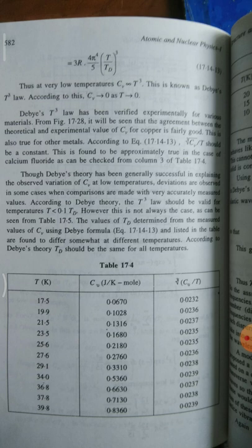Debye's T cube law has been verified experimentally for various materials. It will be seen that the agreement between the theoretical and experimental value of CV for copper is fairly good. This is also true for other metals. According to equation 3, the cube root of CV by T should be a constant. This is found to be approximately true in the case of calcium fluoride, as can be checked from